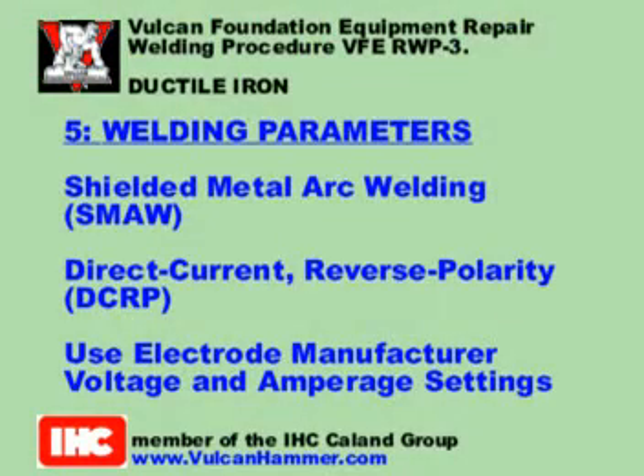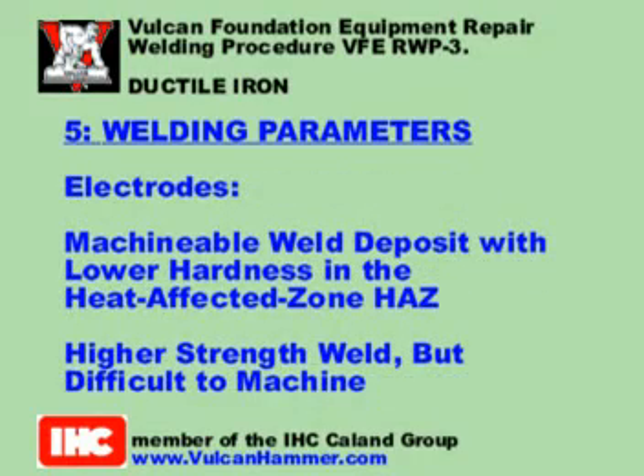Section 5, Welding Parameters. The shielded metal arc welding process SMAW should be used for all welding. Welding current. Direct current, reverse polarity DCRP is required for the electrodes recommended. The voltage and amperage settings should be based on the recommendations of the electrode manufacturer.